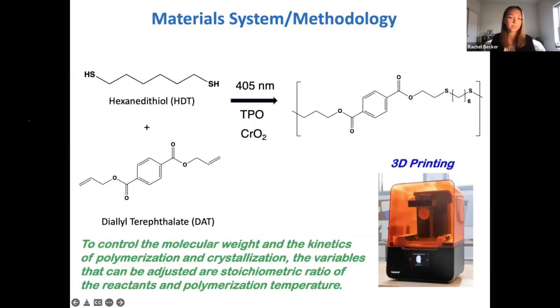So materials used throughout this project are hexane dithiol or HDT and diallyl terephthalate or DAT, which make up both the thiol and the ene components of the thiol-ene click reaction. And this reaction was photoinitiated by TPO, and with the use of chromium oxide nanoparticles, we're able to use induction heating to melt away this mold, which I'll talk about in more detail a little later on. But in order to apply this material to cast molding, we need a low viscosity material with a metallic component for the induction heating. And we also need the 3D printing to have high resolution. To achieve these properties, we are able to adjust the molecular weight and kinetics of polymerization and crystallization by adjusting the stoichiometric ratio of the reactants and also the polymerization temperature.